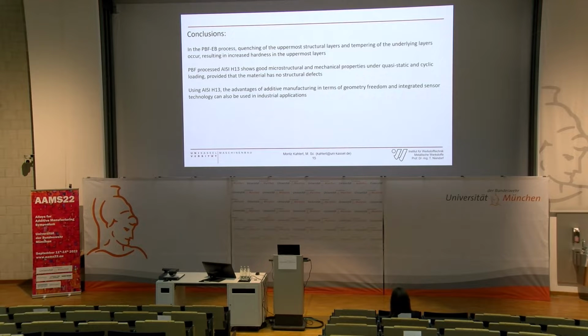Let me conclude by saying that in the PBF-EB process, quenching of the outermost structural layers and tempering of the underlying layers occurs, resulting in increased hardness in the uppermost layers. The PBF-processed AISI H13 shows good microstructure and mechanical properties under quasi-static and cyclic loading, provided that the material has no structural defects. Using AISI H13, the advantages of additive manufacturing in terms of geometry freedom and integrated sensor technologies can also be used in technical applications.